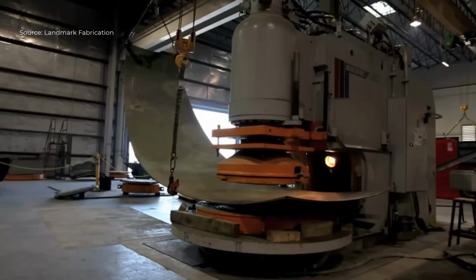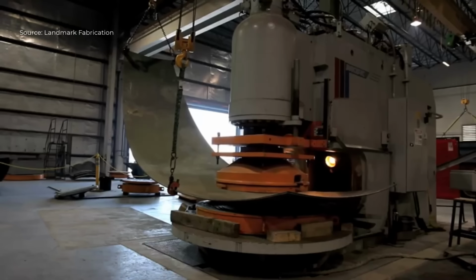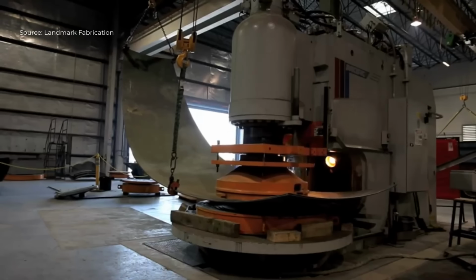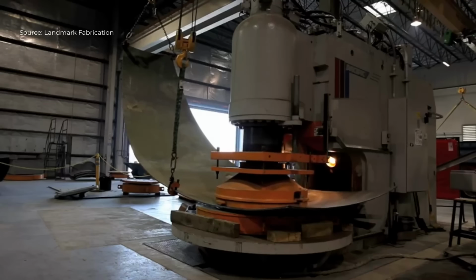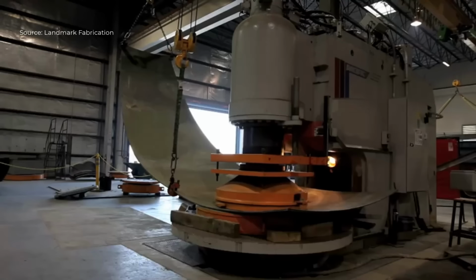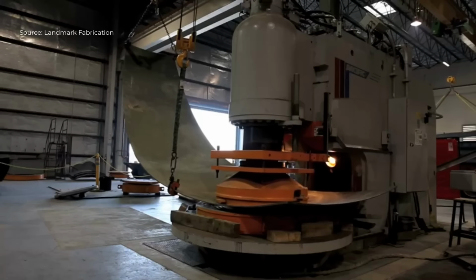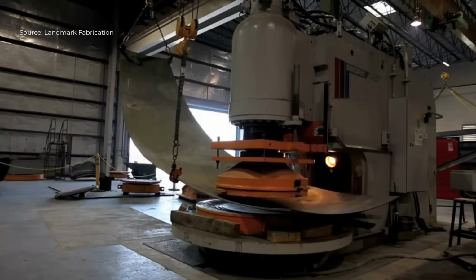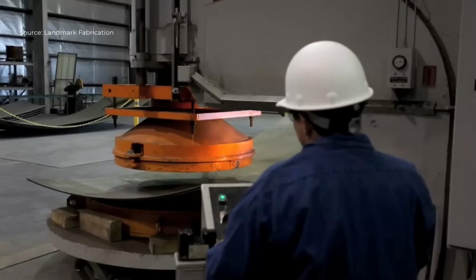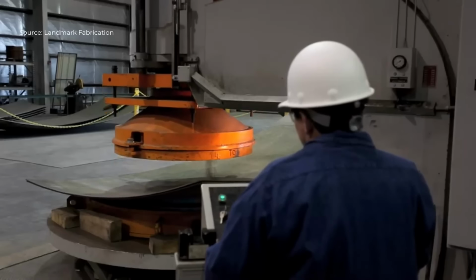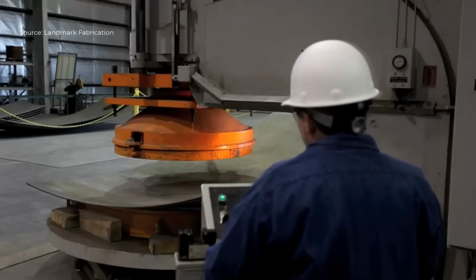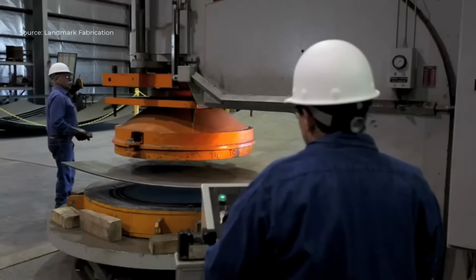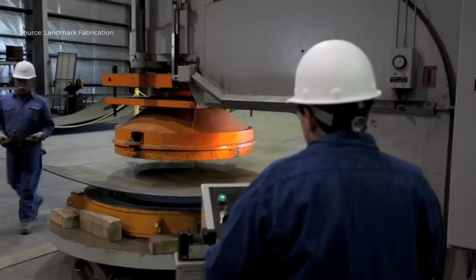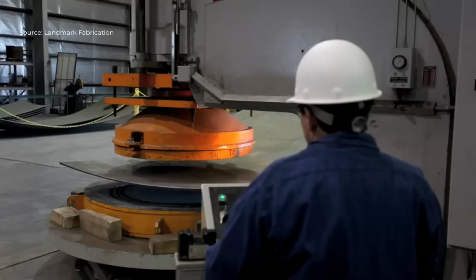The plate is positioned beneath custom dies designed to create double-curved, spherical contours. As the press descends, it exerts up to 750 tons of force, carefully dishing the steel into the desired curvature. Landmark's equipment can handle plate thicknesses ranging from 3/16, approximately equals 4.8 mm, up to 3 inches, approximately equals 76 mm, enabling custom-formed shapes across a range of sizes.